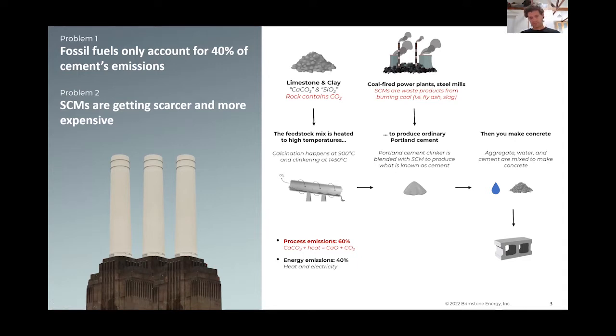So then the other 40% of CO2 emissions from making cement comes from this heating. So you have to heat to 900 degrees C, which is actually where the major energy consumption is. And then you heat again to 1450 degrees C, or further to 1450 degrees C, in order to make the final Portland cement product. And that's cheapest done by burning a fossil fuel. And so that's what's done today.